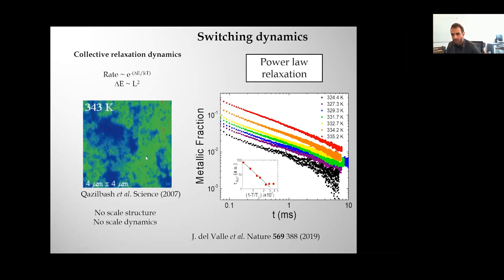paper. In green is metallic, in blue is insulating. This is a SNOM image. And what you can see here, and this is very typical from first order phase transitions in the phase coexistence regime, is that you don't have any characteristic length scale. There are domains of all possible sizes. So that means that no scale in the structure would explain why we observe no scale in the dynamics in our case.